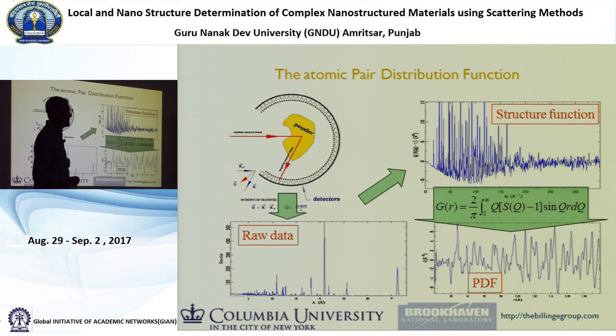But it turns out that this is a perovskite material and it has an octahedron in it with a manganese in the middle and oxygens around it. And this is the oxygen-oxygen distance on that octahedron, and it has a very high multiplicity, a multiplicity of 12, because of the edges of the octahedron. So there's a very high probability of finding two atoms separated by this distance. Each of these peaks in here tells you how atoms are separated. And so this is like a one-dimensional map of the inside of your material.